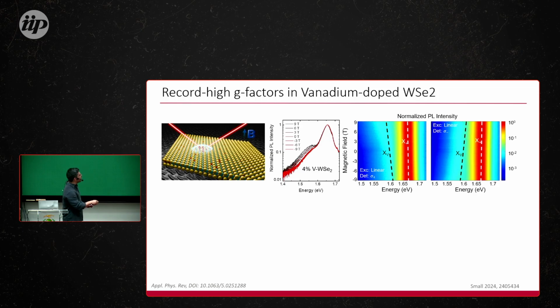We have one more quite interesting feature here. You can see the peak is not so sharp. So there is also some kind of doping that can come from the substrate, since we use a silicon substrate. So we have the trion. A trion is just an electronically charged exciton, okay?